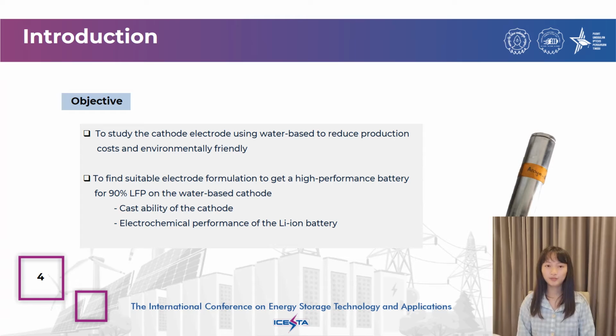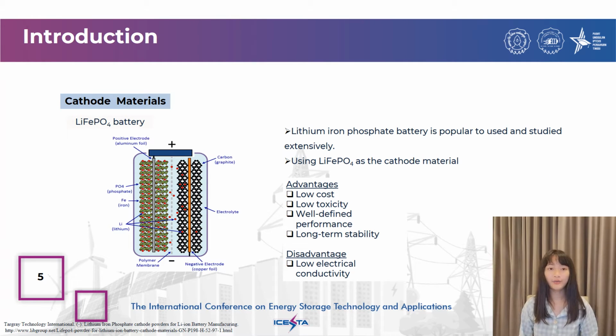The objective is to study the cathode electrode using a water-based solution to reduce the production cost and improve environmental friendliness, to find a suitable electrode formulation to get a high-performance battery with 90% LFP using a water-based cathode that has the castability of the cathode and electrochemical performance of current lithium-ion battery cells. This study will use water as a solvent with the following components: 90% lithium iron phosphate with 10% conductive and binders.